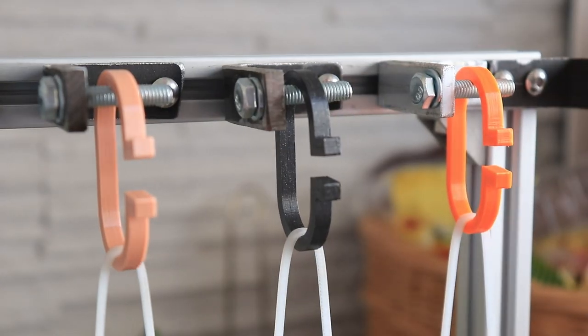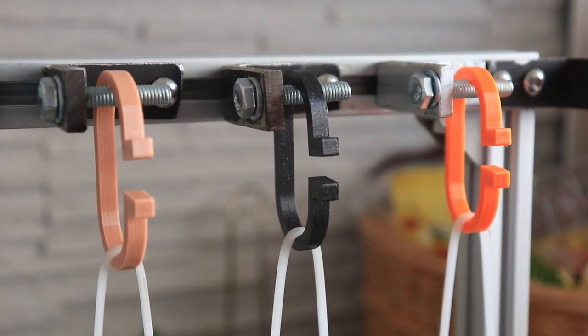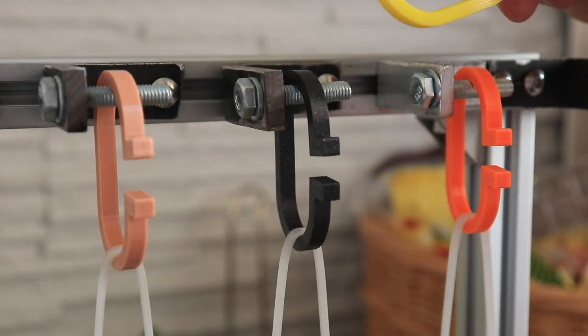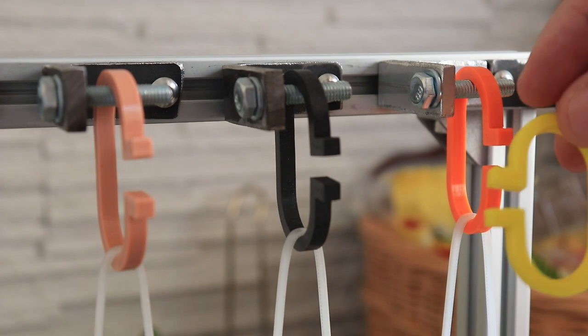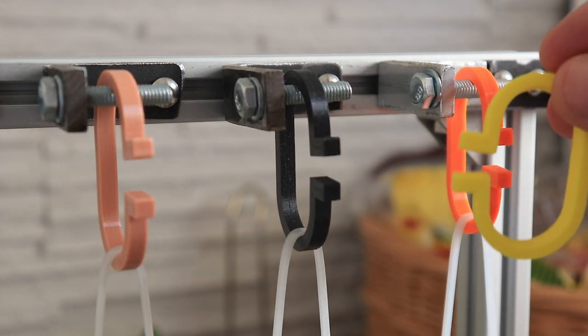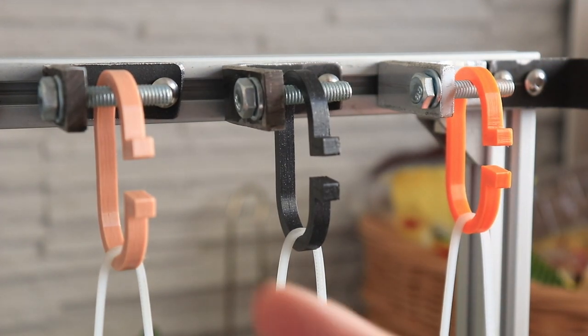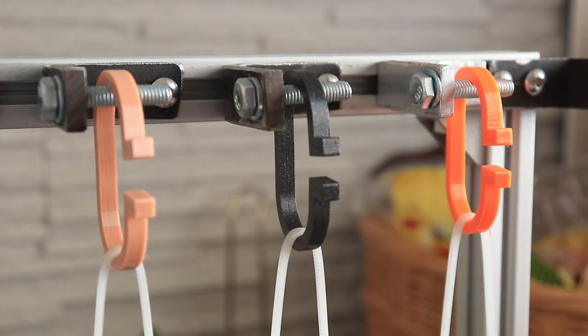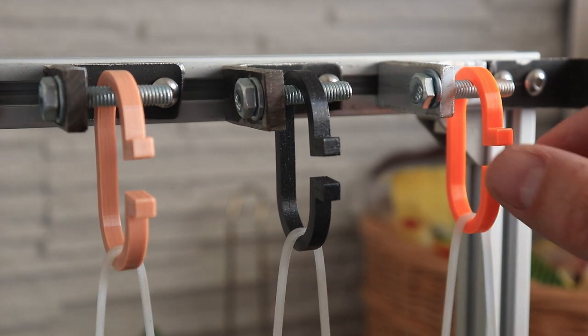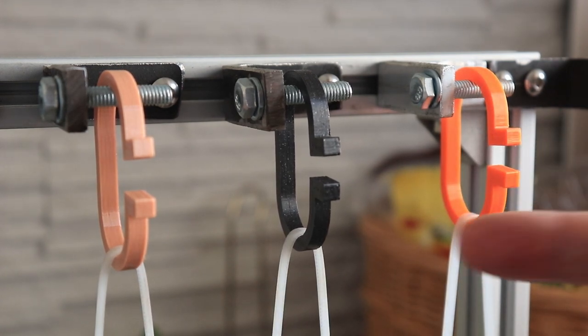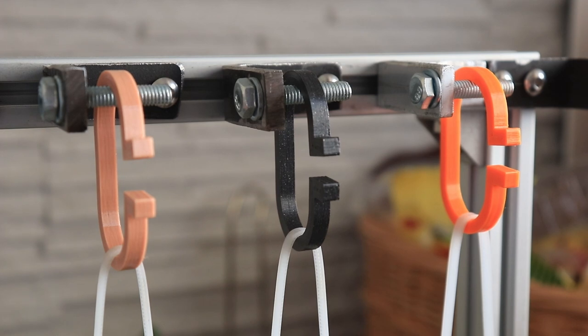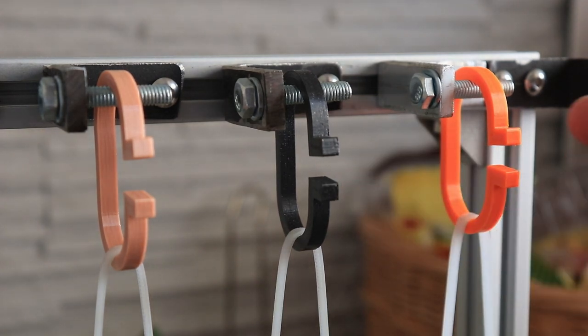So I measured everything. And yeah, this is the first time I went up to 50 degrees Celsius on this test, and the PLA became soft and it fell down. But look at this, it became well, near the original shape. Now I can see the biggest deformation on PETG, that was not a surprise, but interesting that I measured more deformation on the PC blend compared to the ASA. So for the creeping, the ASA is better than the PC blend.